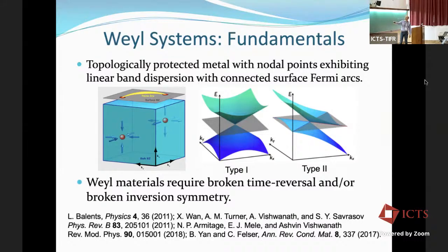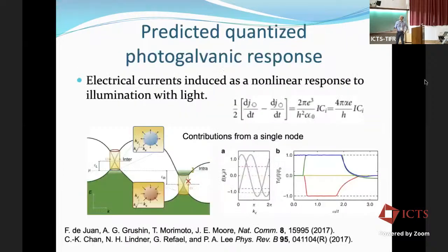And what's important is that these cones can be tilted. So they're not necessarily symmetric with respect to this gray plane. They can be tilted with respect to that. And if you tilt them so far that they actually tilt through the plane, then the Weyl point is changed to a different type. So we have so-called type 1 and type 2 Weyl points. In addition, there is a topological charge associated with the nodal point, which can take different values, 1, 2, 3, or 4 in particular. So there's both the tilt and the charge. And what we're interested in exploring is, what are the signatures of the tilts and charge in experiment.